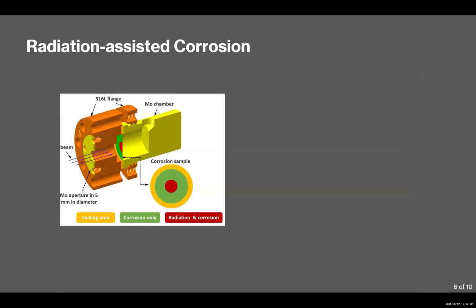Okay, so the corrosion stuff, we have this little cell. You've got liquid metal on one side of this foil, which is this target looking device. So there's a little foil of metal. We've got liquid metal in this case on one side of the foil and high vacuum on the other. We're shooting irradiation through, seeing what happens in a certain irradiated region versus unirradiated.